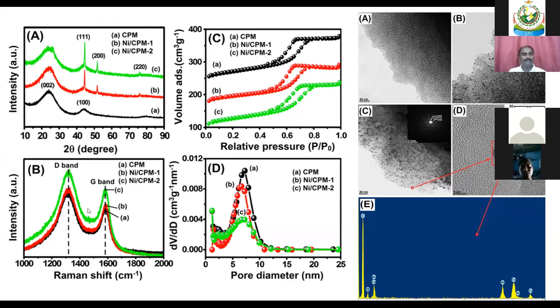Another is the Raman shift, the Raman studies. You can see the three composites and the corresponding peak profiles. And this is the TEM image. It's the bare carbon. You can see the holes present in the TEM image of bare CPM. And after mixing the nickel acetylacetonate, finally we get the nickel composite. You can see very, very fine nanoparticles, about 5 nanometers in size, present only as nickel 0, not nickel oxide or other metal oxides. And this is the EDX spectrum of the corresponding composite.